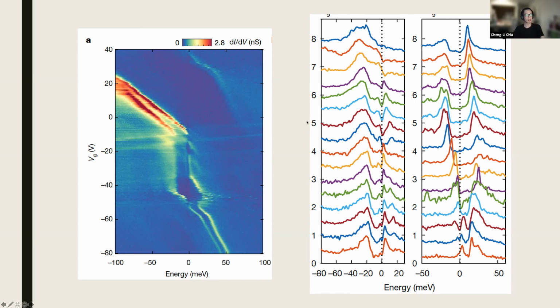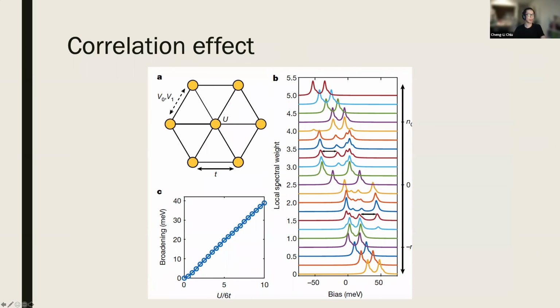When we are doping the band structure, it shouldn't change shape if there's no interaction effect. It should just be a constant shift because we are changing the Fermi level only. However, you see when these two flat bands get close to the Fermi level, it suddenly changes the shape. Even the intensity has changed dramatically. And you can see here, the band has even split into two. This is an indication of some strong correlation effect. We can use some theoretical modeling to simulate the effect, and we confirm that in this device, we do have a strong correlation effect.